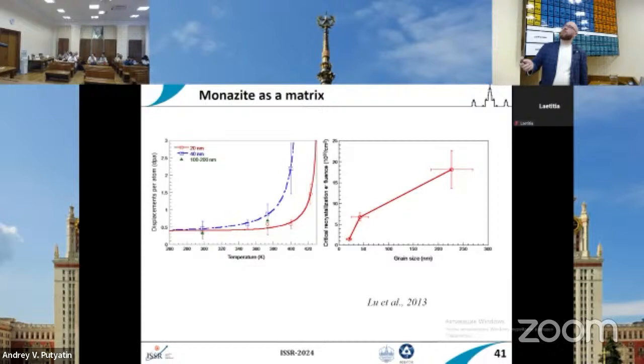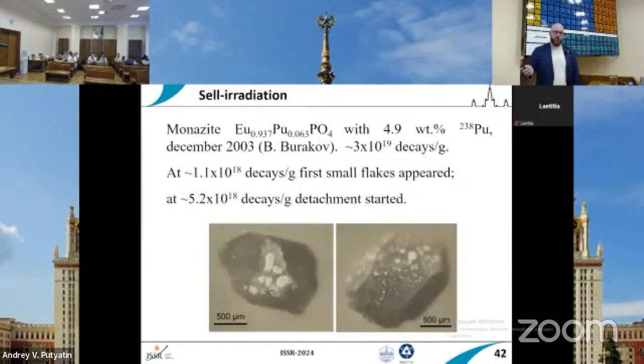Okay. And you can see that with the higher size of the crystallites, the material becomes more stable. And it is one of the good real examples of these monazite-like matrices. It was synthesized by our colleagues in St. Petersburg in the Radium Institute by Boris Burakov. It is europium phosphate, so it's monazite, doped with some plutonium, up to 5% mass percent of plutonium, so it's high enough.